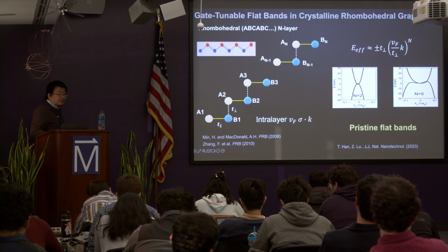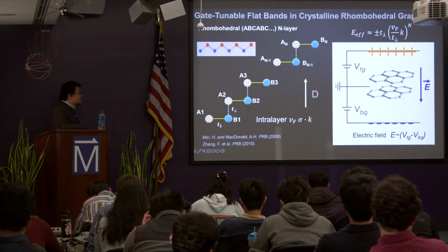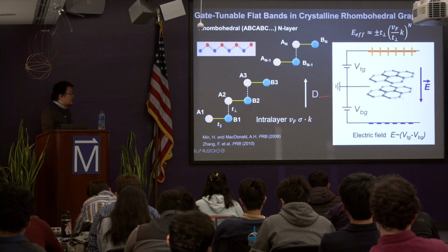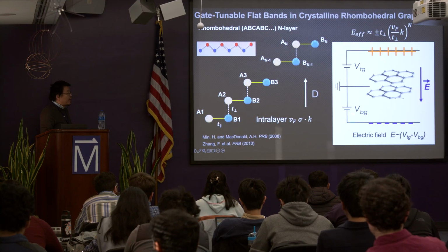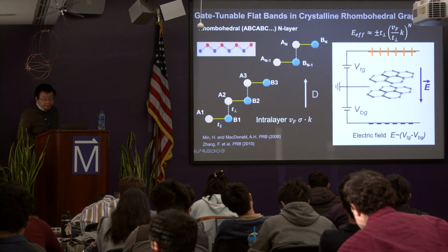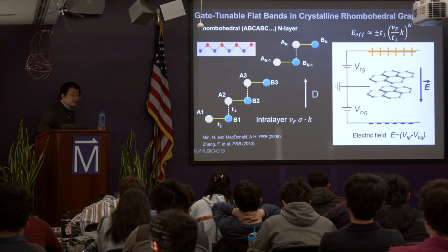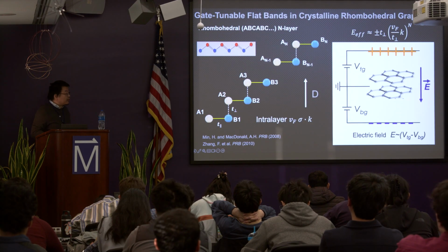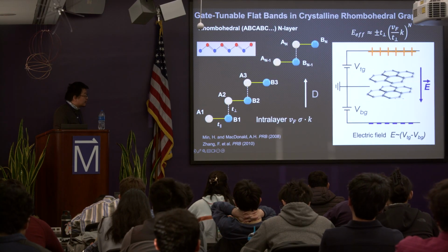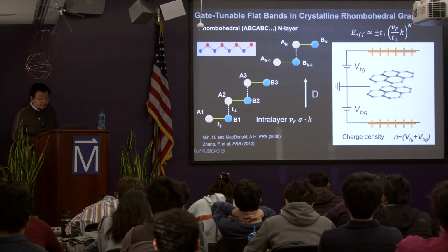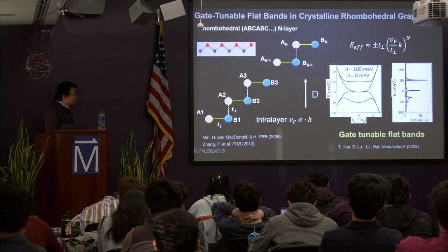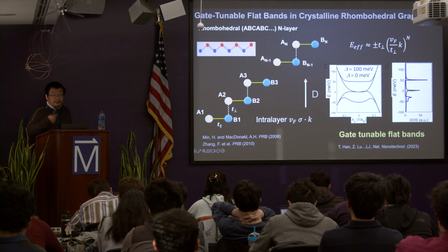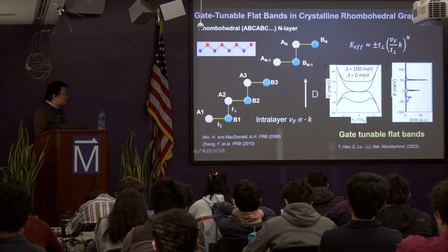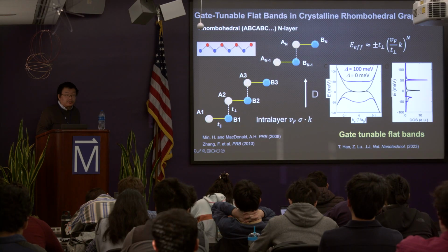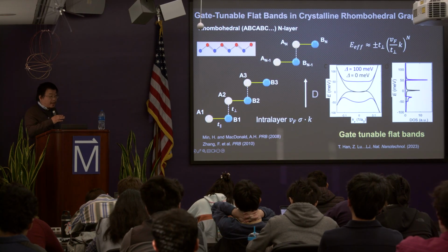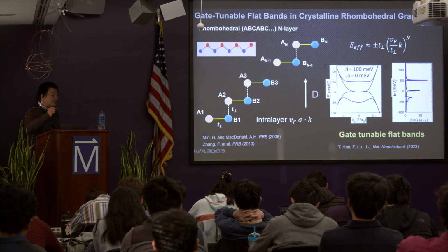Because it's a 2D material, we can utilize the advantage of van der Waals materials to form a parallel plate capacitor structure. You sandwich whatever material you're interested in between two dielectric layers, and then you add two metal layers on top and bottom to form this parallel plate capacitor. Then you can individually change how much you dope electrons or holes, or how much you change the electric field. If you put different charge on the two sides, then you're adding an electric field, right? If you put the same charge, then you're changing the doping. By adding the electric field in the rhombohedral graphene, you're breaking the inversion symmetry and opening up the band gap. At the same time, you can also tune the bandwidth, how flat it is. So you have naturally existing relatively flat bands, and then you have a continuous knob that you can use to tune the flatness of the bands.